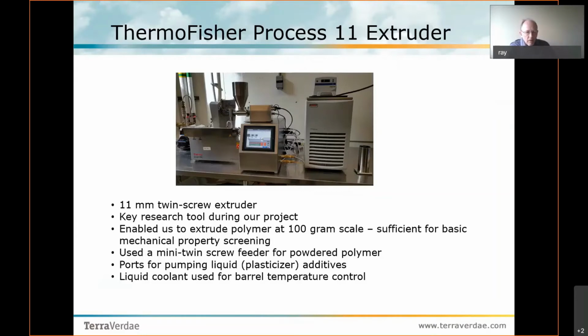We needed this to just get a sense for where we could go with our PHAs, and it enabled us to also extrude polymer at as low as 100 grams at a time. And even at that scale, we were able to produce sufficient filament and material so that we could do basic mechanical property screening. And that's the route we took.